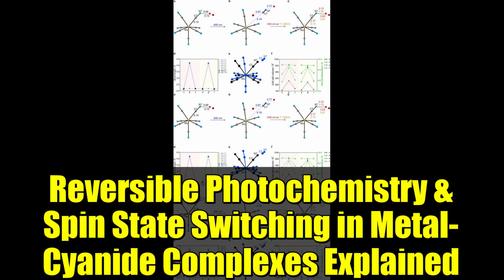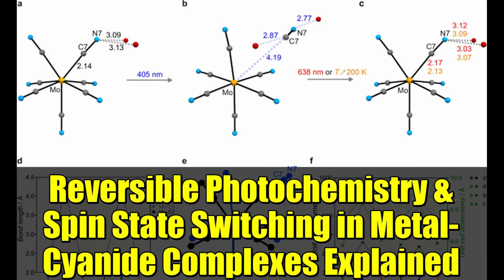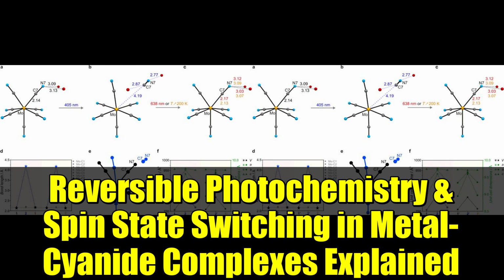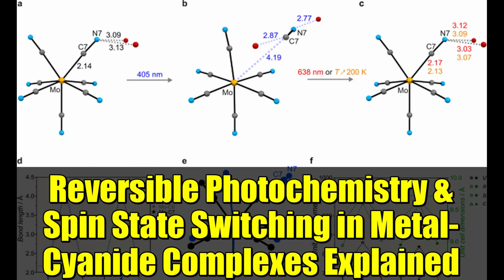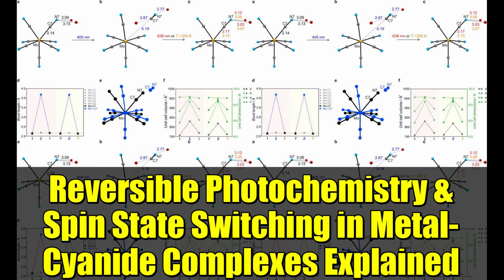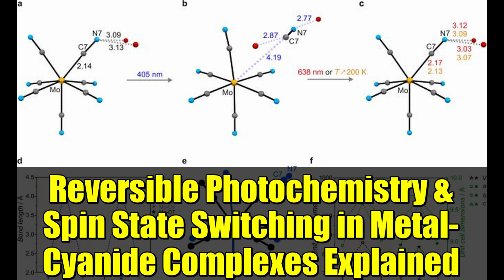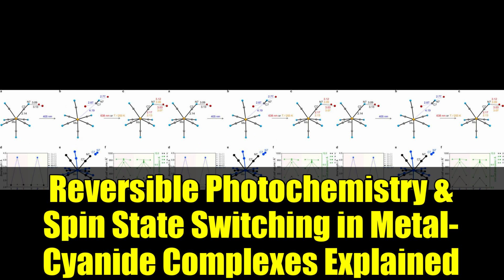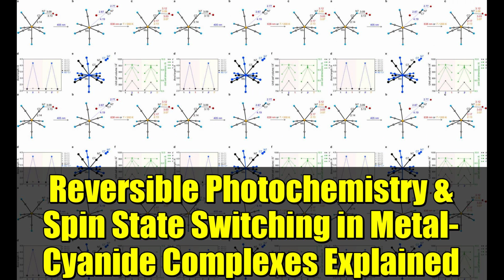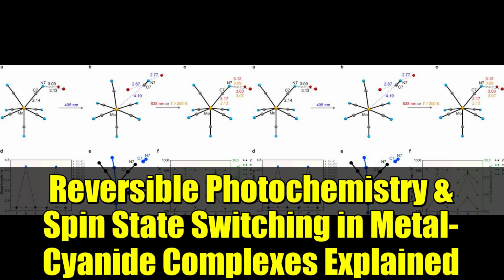In summary, a single crystal of the inorganic compound K4Mo(CN)7·2H2O demonstrates a reversible photochemical reaction, enabling the molybdenum center to switch between the 7-coordinate low-spin and 6-coordinate high-spin geometries. This bidirectional photoswitching is remarkably robust and non-destructive, yielding colossal structural, electronic, and magnetic changes. Interestingly, photodissociation in solution is irreversible, permitting isolation of the hexacyano Mo(III) complex.